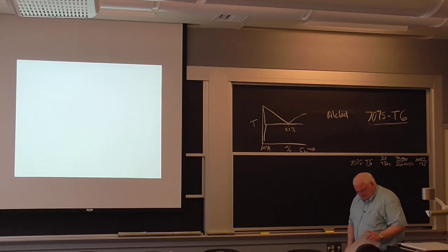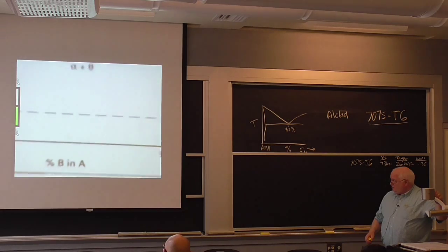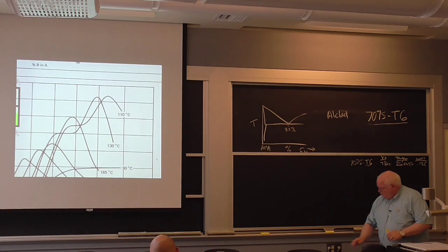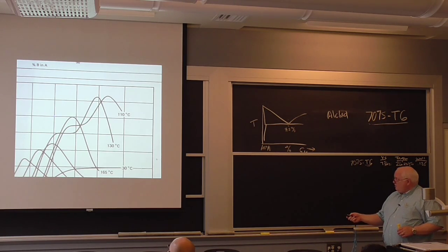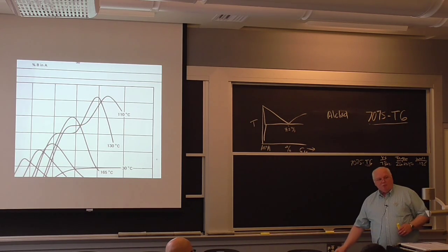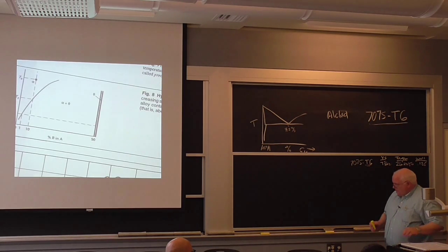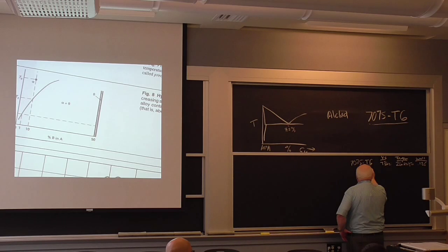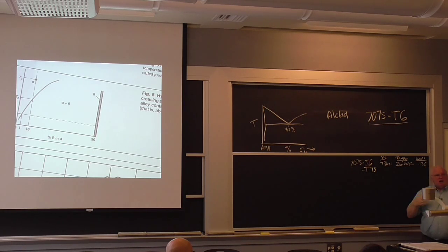If on those annealing curves that I showed you, we went and overaged just past the peak, okay? If we were on this curve right here and we went just past the peak to right here, we could sacrifice a little strength and get a lot more toughness proportionally, okay? And that's called a 7075 T73 heat treatment. T7 heat treatment means slightly overaged. T6 means optimal aging, maximum strength. T7 is optimal aging for high strength and corrosion resistance.